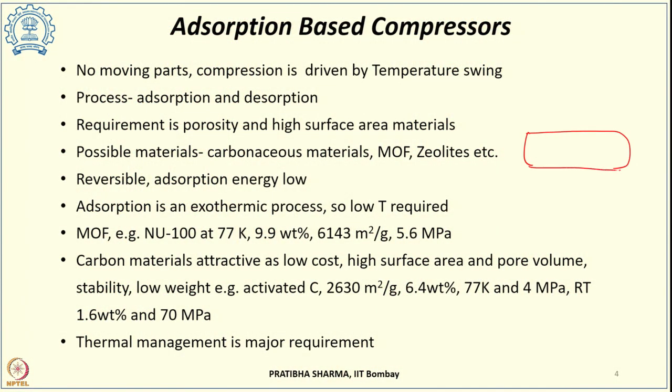When a low pressure gas is introduced into a closed tank which consists of high surface area materials and high porosity, the hydrogen gets adsorbed onto the surface of those high surface area materials. This adsorption is a surface phenomenon, and once it reaches saturation, a desorption process can be initiated to get high pressure hydrogen. For desorption, heat energy input has to be provided, which increases the temperature of the system and the adsorption bed, thereby desorbing hydrogen.